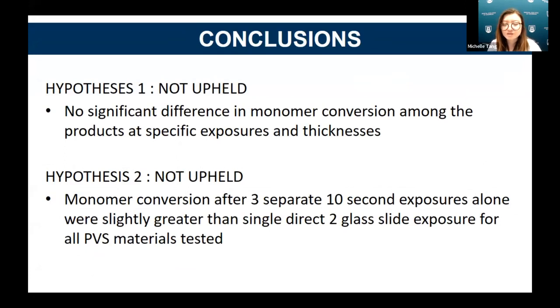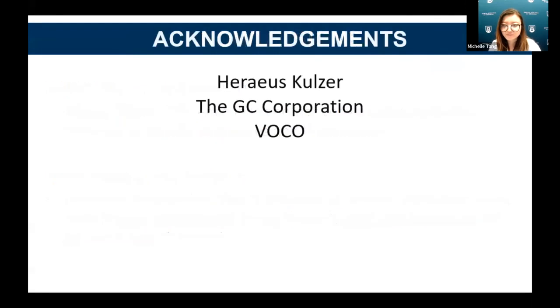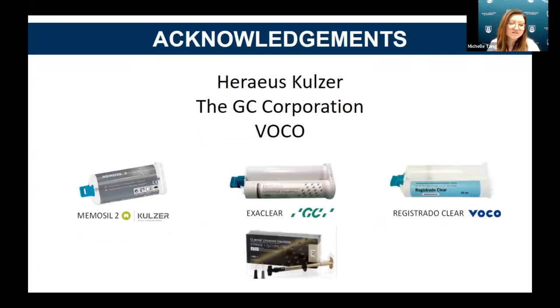Furthermore, the second hypothesis was also not upheld, as monomer conversion after 3 separate 10-second exposures proved to be slightly greater than the control group for all PVS materials tested. The results of the study would indicate that clinicians using the BFEP technique may not have to worry about the effects of PVS and tray material hindering the curing capabilities of flowable composite. It must be noted that all materials used in the study were marketed specifically for this technique, and any deviations cannot guarantee similar results. We'd like to acknowledge all of the companies that supported our study, and thank you so much for your attention. I will be taking questions now.